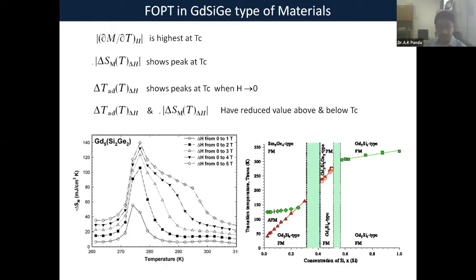So basically, what I mean to say is, typically the first order magnetic transitions in gadolinium silicon germanium, when both the magnetic and the structural transformations reinforce together, you find a peak, and that peak goes on increasing with the intensity of the applied field. You see in the left plot that 5 Tesla has the highest entropy, and the entropy goes on decreasing as you reduce the field. Now these are all under consideration when you make a device for a technology.